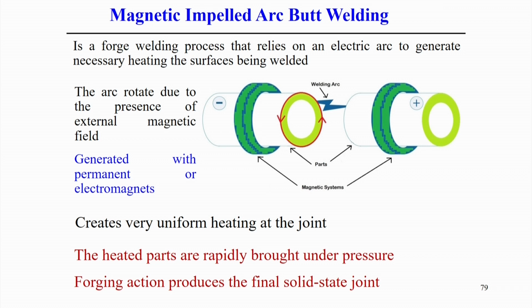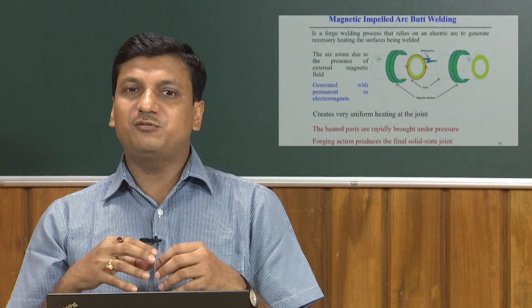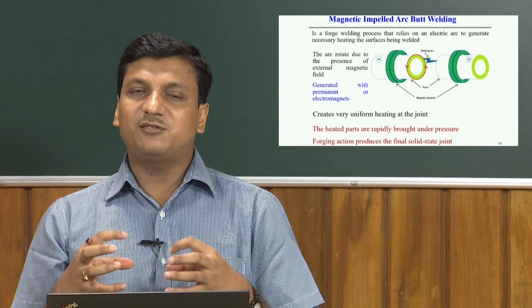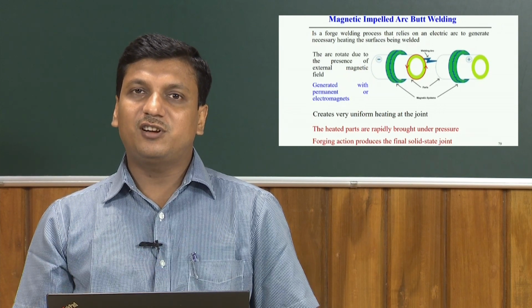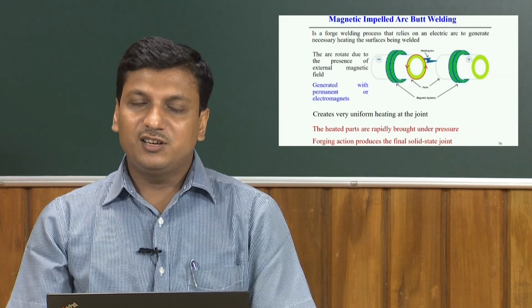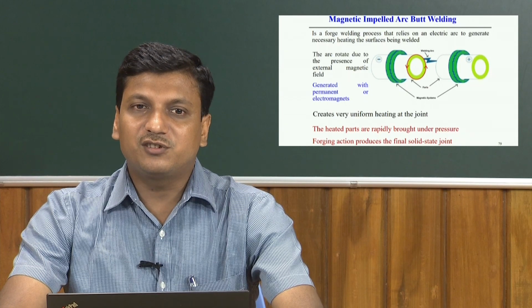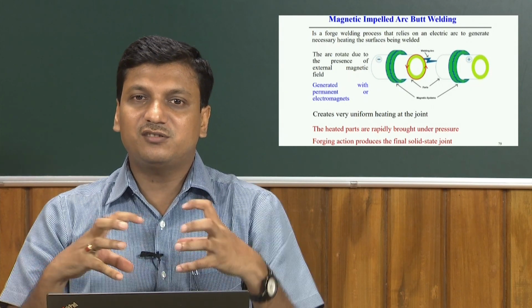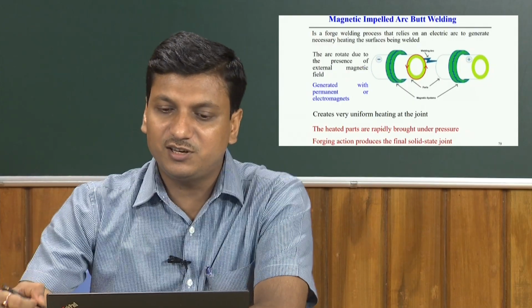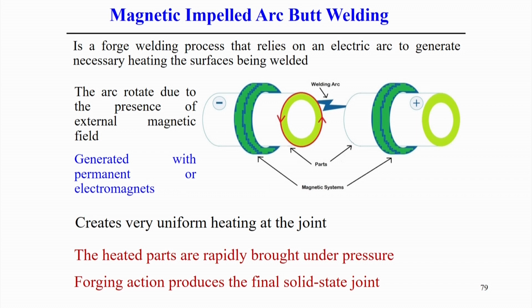So, what is the principle of this process? It is basically a forge welding process that relies on the electric arc to generate the necessary heating, though sometimes small melting can also happen at the surface being welded. First we uniformly heat the surface, and then we bring the surfaces into contact by the forging process, and then it becomes welded. Mostly cylindrical components are used. If you see the figure, two cylindrical components can be joined here.